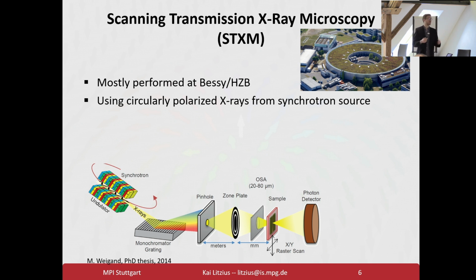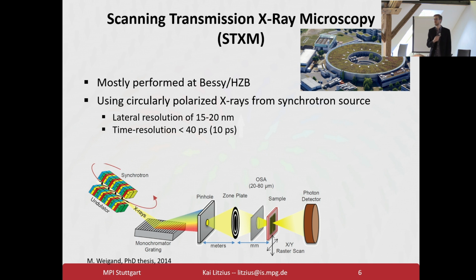The cool thing is that we pick up all the information on the magnetization within the spot size on the sample, and this is usually in our case between 15 and 20-ish nanometers. And by pump-probe means, we can also do time-resolved imaging of reproducible processes with a time resolution of 40 to 10 picoseconds, more or less.